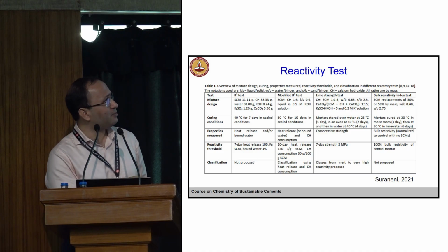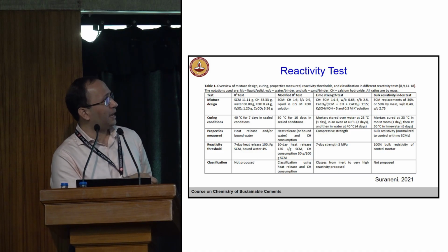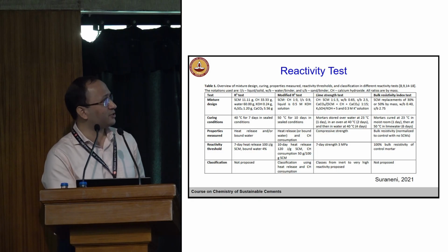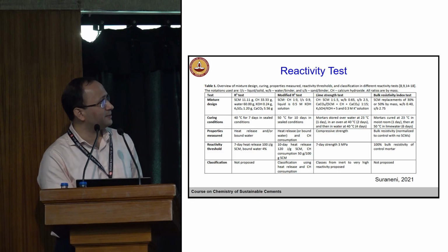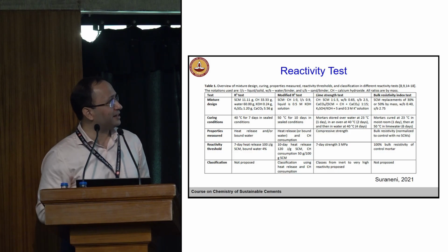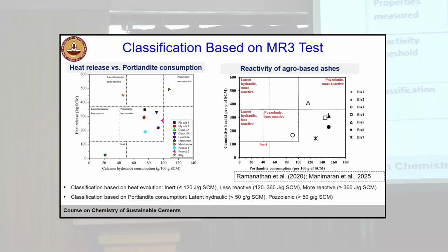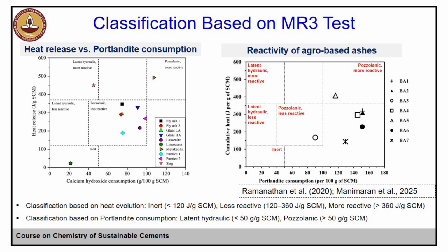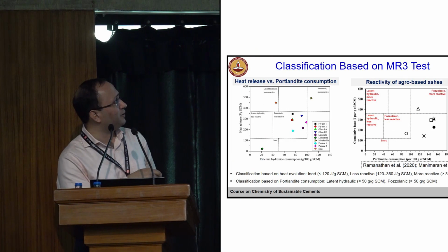Okay, then you have the lime strength test. You simply add lime, right, calcium hydroxide, and then you look at the strength of mortars. Then the bulk resistivity index test is also there. So I will just show you some of the interesting results. This was again done using MR3, modified R3. It can help you differentiate different types of SCMs.